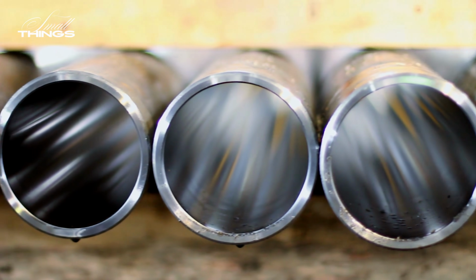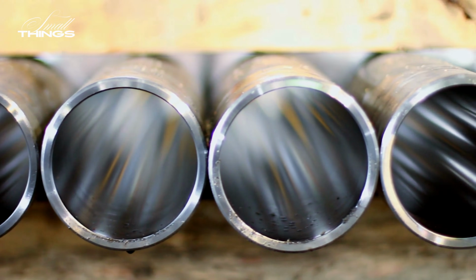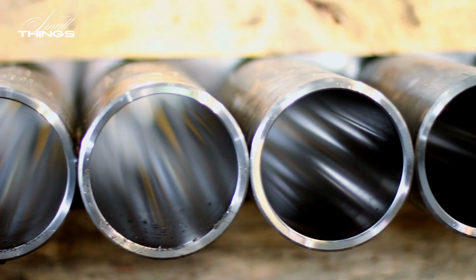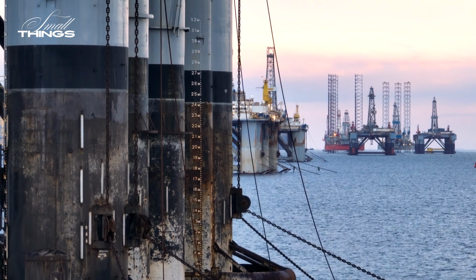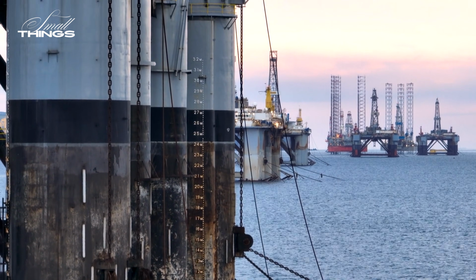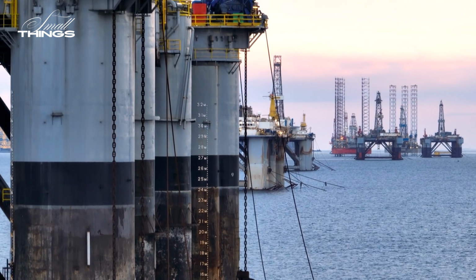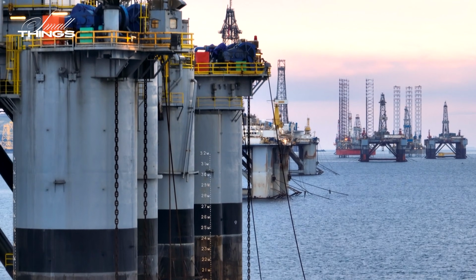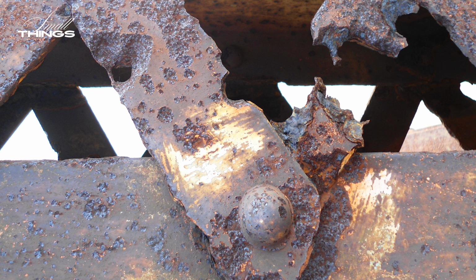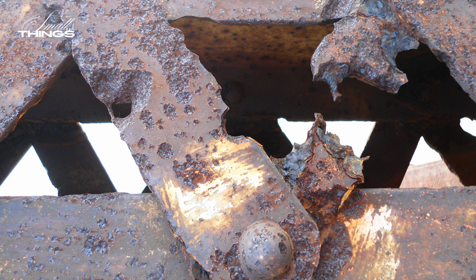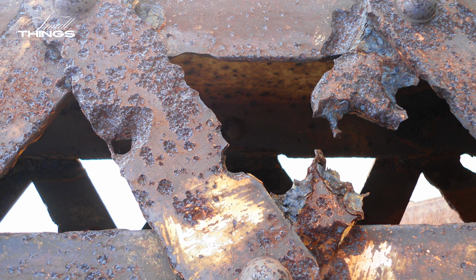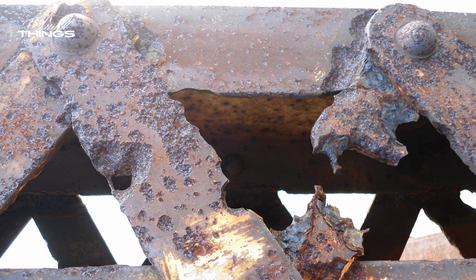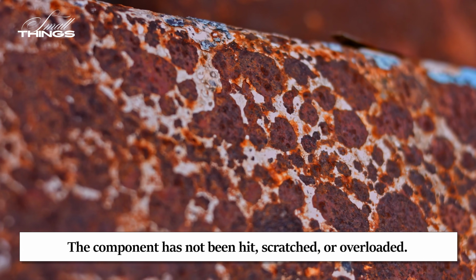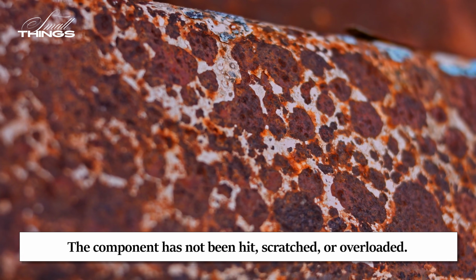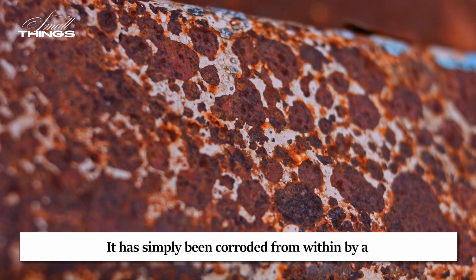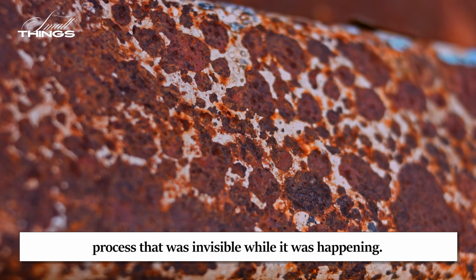At normal temperatures and pressures, stainless steel handles this well. But at higher flow velocities, at raised temperatures, under mechanical stress, or when the seawater is carrying dissolved gases like hydrogen sulfide found in offshore oil environments, the conditions tip. The passive film fails. Localized pitting begins. In some cases, the pitting progresses into cracking that spreads through the metal's grain structure. The component has not been hit, scratched, or overloaded. It has simply been corroded from within by a process that was invisible while it was happening.